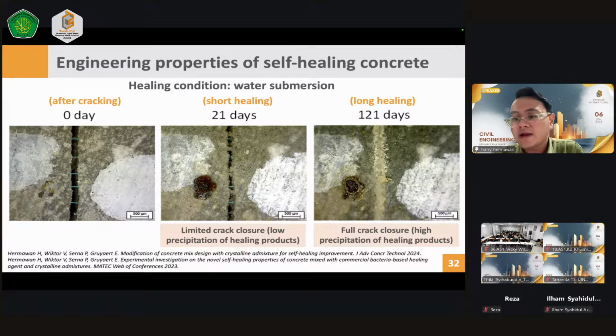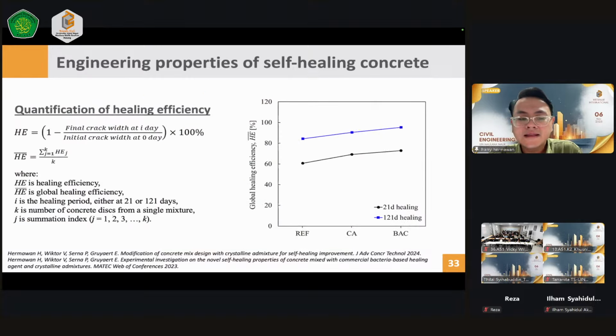And how can we evaluate the healing process quantitatively? Typically we calculate the so-called healing efficiency. If you look at the formula, healing efficiency, or HE, is 1 minus the final crack width at a certain time divided by the initial crack width after cracking at 0 day, times 100%.